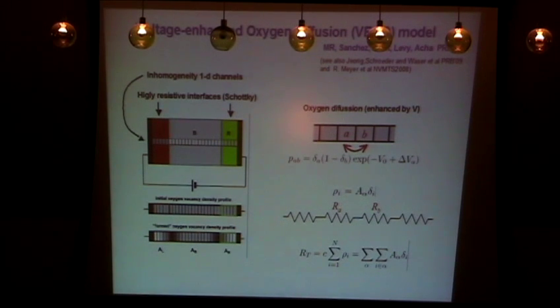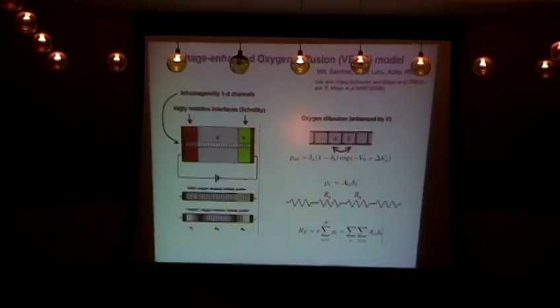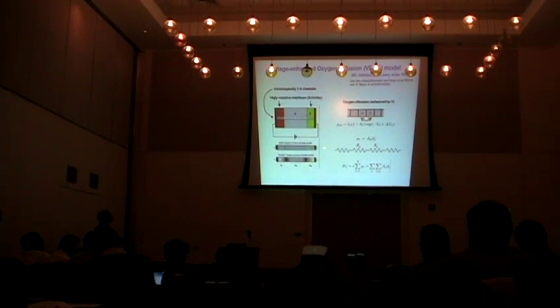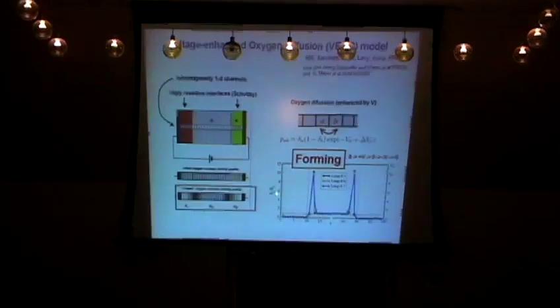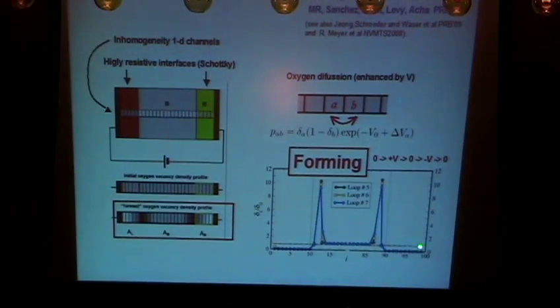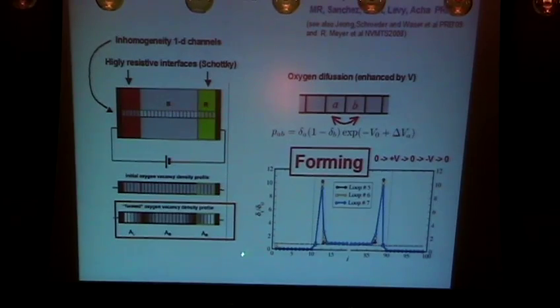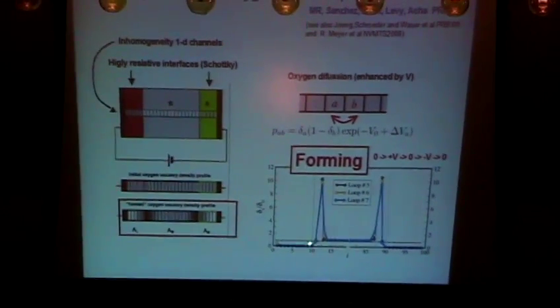Okay, the first surprise is that if you start with the model with homogeneous resistance, which is natural for a system in an as-is preparation, you just take it from the oven, and all the concentration of vacancies should be homogeneous. So you start with a density of vacancies which is homogeneous. This is the shade of gray. And after doing the forming, what you find is that the density of vacancies changes dramatically. They get depleted from each one of the two interfaces, and they accumulate in the inner side of the bulk region. So here you have the density relative to the initial one. We start with a homogeneous value of 1, and what you see after the forming steps is depletion of the two interfaces and accumulation up there.